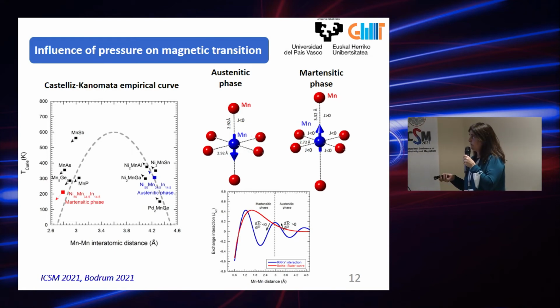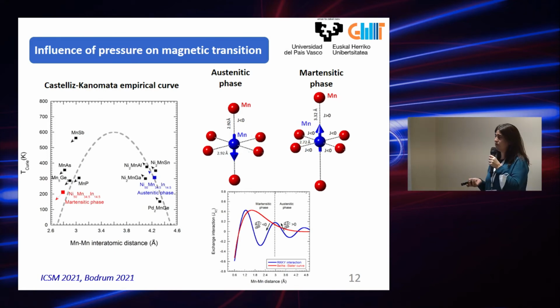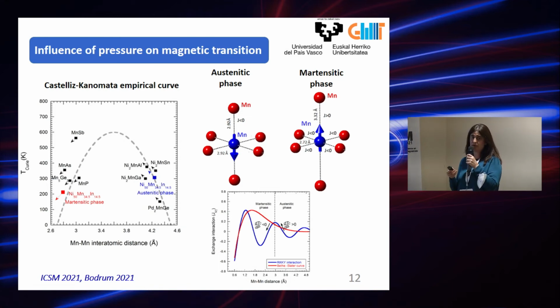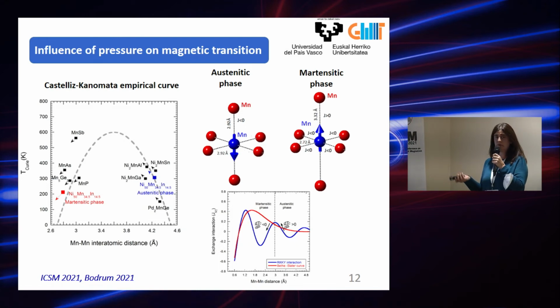Okay. We have spoken until now about this structural transformation, but there is also an interesting result, which is the influence of this pressure on the magnetic transition. So we saw that there's an opposite tendency, and the Curie temperature is increasing in the case of the austenitic phase, but decreasing in the case of the martensitic one. So this behavior can fit well with this Castelliz-Kanomata empirical curve, and we have here our system that is in the austenitic phase when the pressure increases the Curie temperature, and in the martensitic phase that this pressure decreases this Curie temperature.